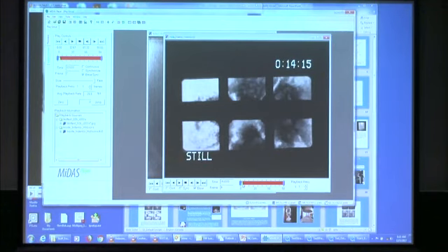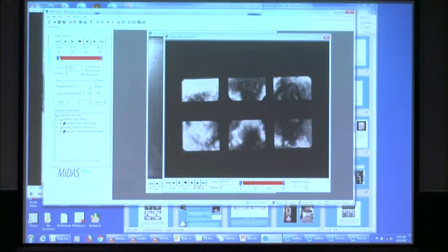So now we're starting to see some features. What's happened here, unfortunately the bracing covers some of the view, but you could see enough. You see that X shape starting to develop, and that's because spalls are happening on the edges of this pyramid. So one spall here, another here, another here, another here. And the X is the pristine ice where the pressure is high, 20, 30, 40 MPa. And the spalled ice, which is beaten up and pulverized, the pressure is around between 0 and 10 MPa.